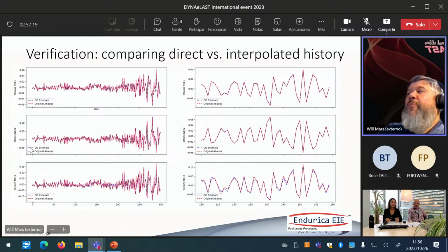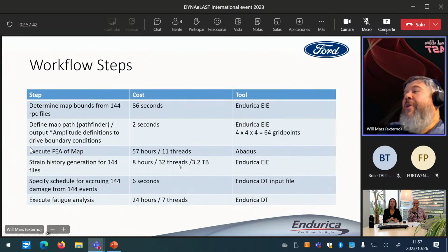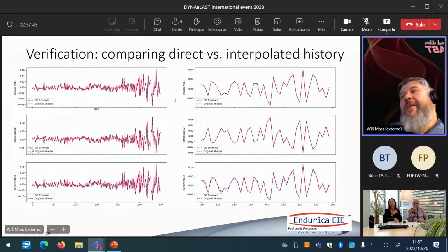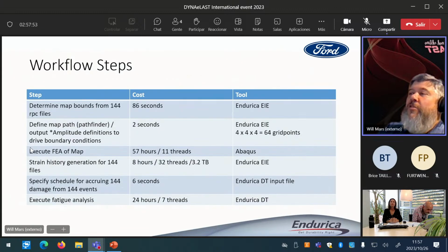Right, there's two lines here, but they overlay each other quite well. The blue line is the interpolated line. The red line is the direct Abaqus solution. On the right, you're seeing basically a zoom up of one portion of this signal, just so you can see better how well the signals agree. So long as your map is sufficiently discretized, you're going to find really good correlation of your strains. But of course, the interpolated strains get computed about 10,000 times faster than you would do in the direct finite element solution.